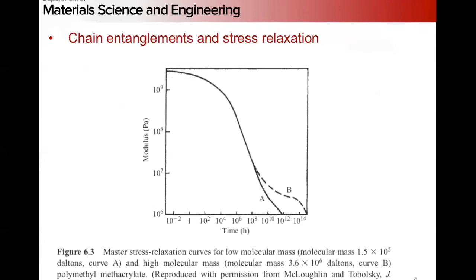So what we can see here, this is experimental curves from PMMA. I'll have the structure of that in a bit when we talk about some of the side chain reactions. But a low molecular weight and a high molecular weight. And for the low molecular weight, we don't see this plateau region, whereas at high molecular weight, we do, right? Remember, this is a log scale here for time, so this is significantly compressed. If this was a linear scale, this plateau would be very extended. Right? So we see basically at these times, potentially, depending on how fast this goes down, an order of magnitude difference in the relaxation modulus as a function of the molecular weight.